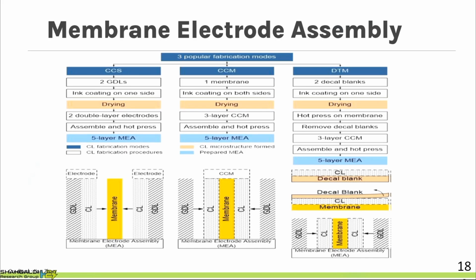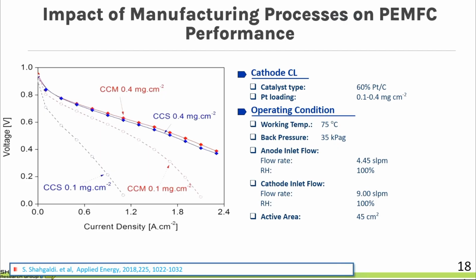CCM is the one where we transfer the catalyst ink directly to the membrane. So what is the problem? Because of the texture of the membrane, when we put the ink on it, the membrane swells or shrinks or changes size. So we need to figure out a way to deposit the catalyst layer on top of the membrane without changing the shape of our membrane. So in order to make this easier, industry selects the decal method. What does it mean? They put their catalyst layer on an inert substrate that is normally Teflon and then transfer it to the membrane. So that goes through a roll-to-roll machine. So also we did try a lot for the CCM, decal, and CCS, to understand which method is best for making MEA.